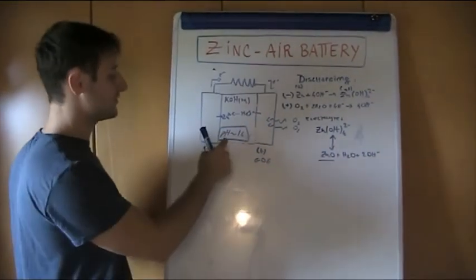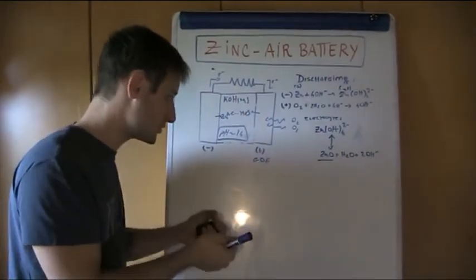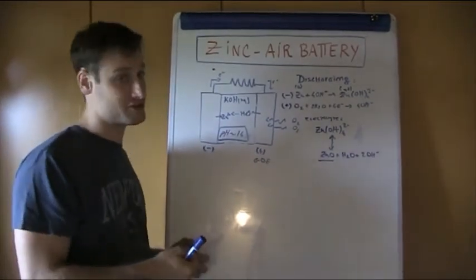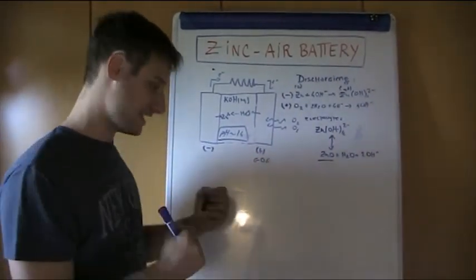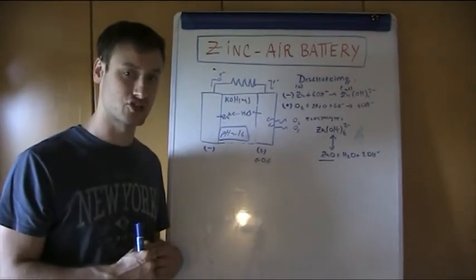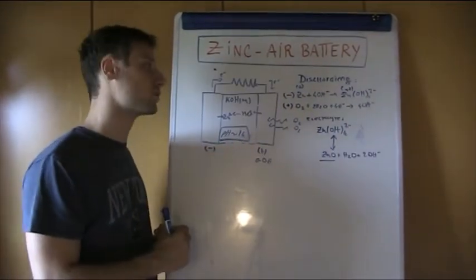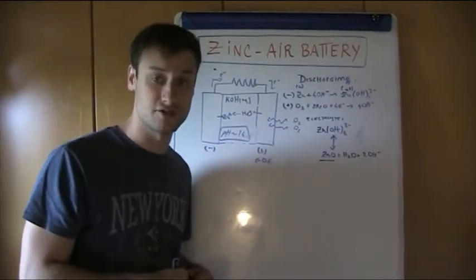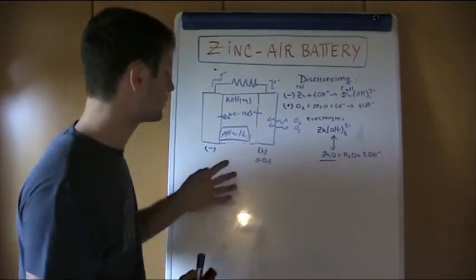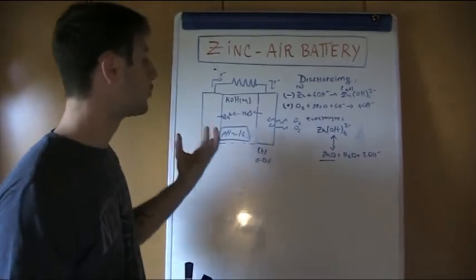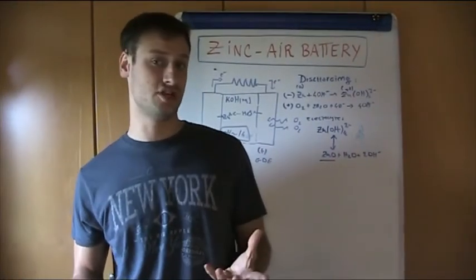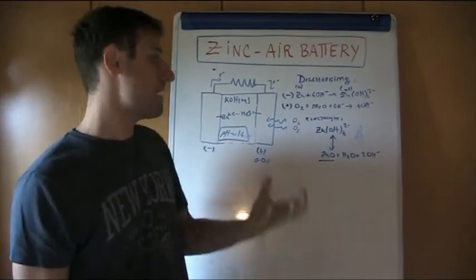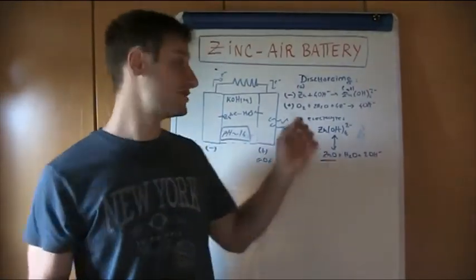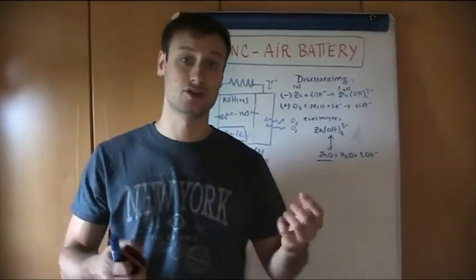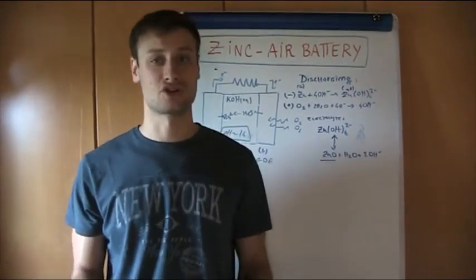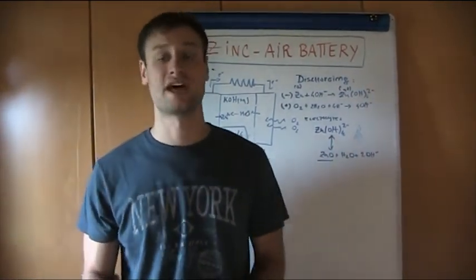It's crucial because this value of pH allows us to promote the formation of zincate with respect to insoluble hydroxide and inhibit the hydrogen evolution reaction. That is something that is not negligible considering the reduction potentials of the zinc reaction. What does it mean? In order to understand these concepts and why it's so important to work in super alkaline conditions, it's important to remember the Pourbaix diagram of zinc and look at what types of side reactions involving the corrosion of the electrode can be present.